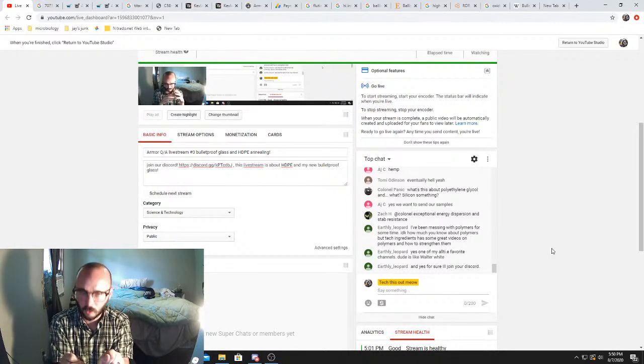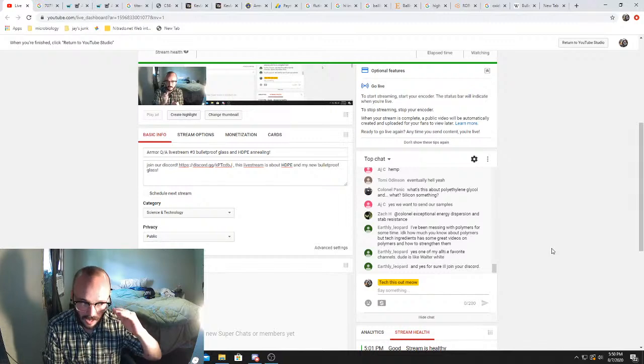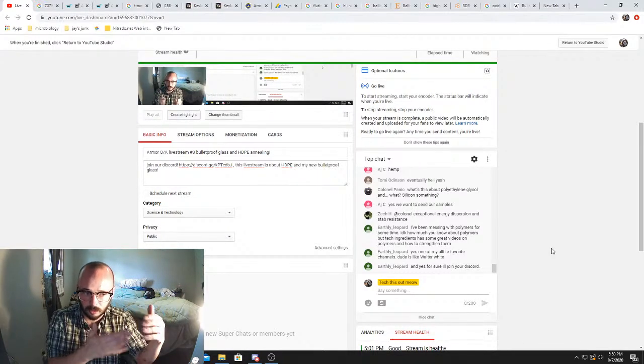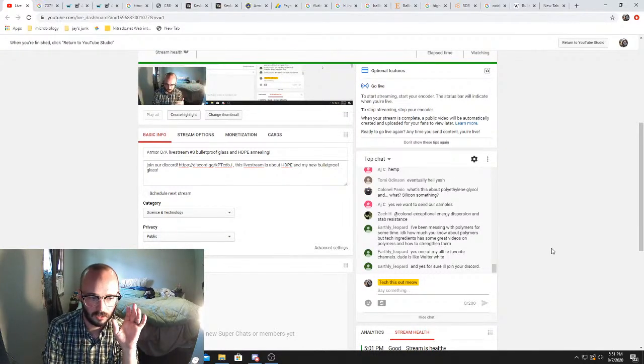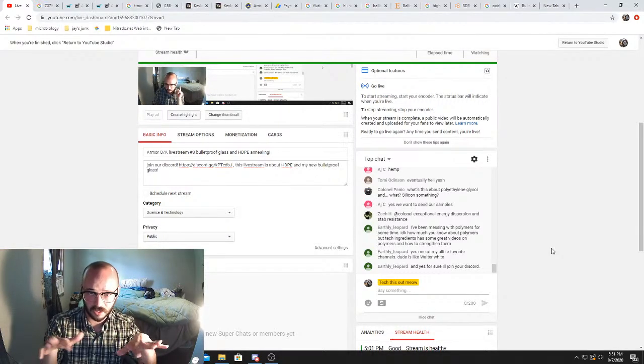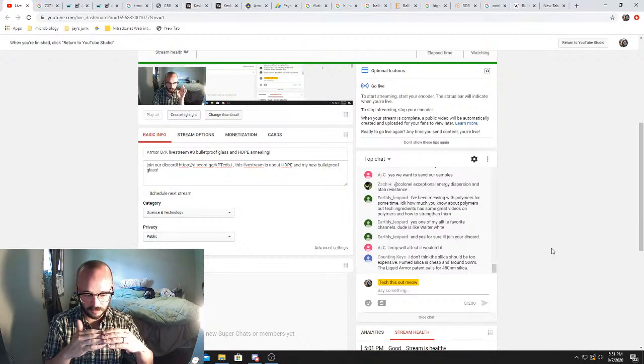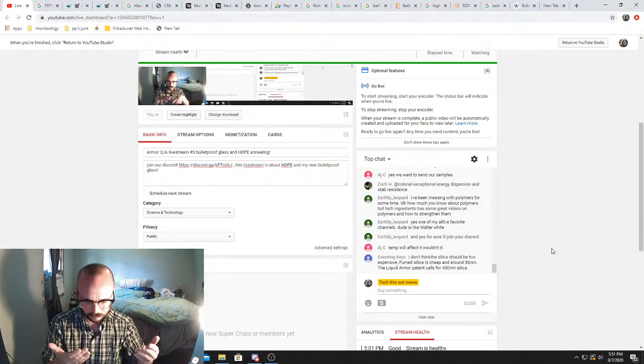But if you try to quickly snap it, it would solidify into a hardened shell. That is the absolute highest idea of a shear thickening fluid, a non-Newtonian fluid at its 10th degree. The problem with it is they are very temperature dependent. You go over a certain temperature range, those particulates that are suspended in the solution, the silica in the polyethylene glycol in this instance, they separate too much because they're agitated because of all the heat.